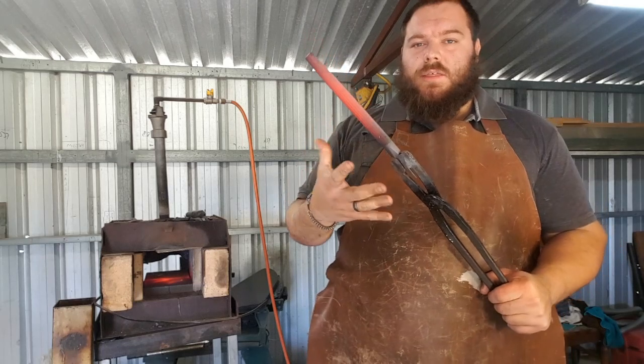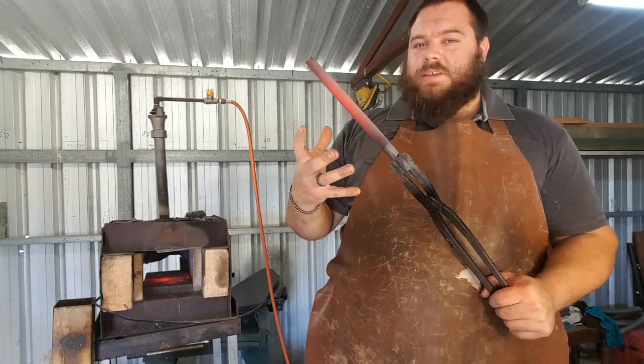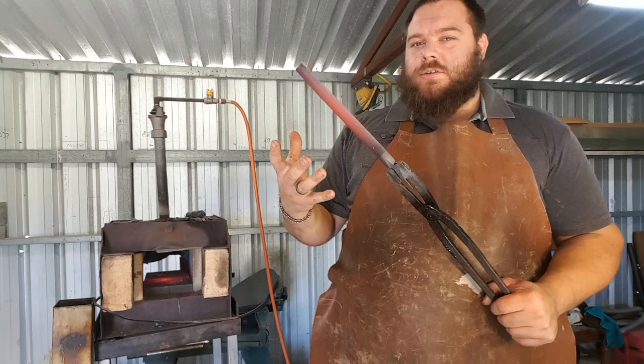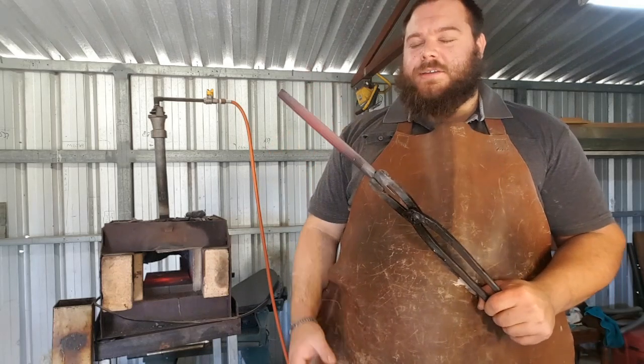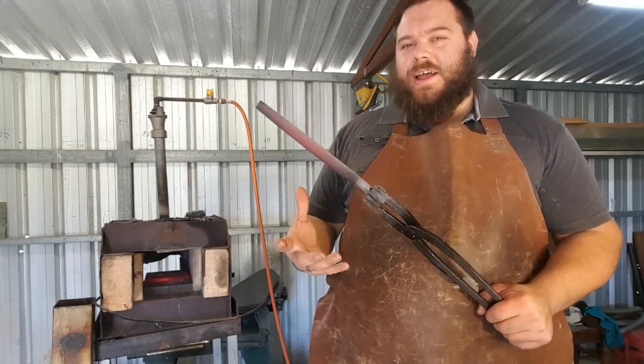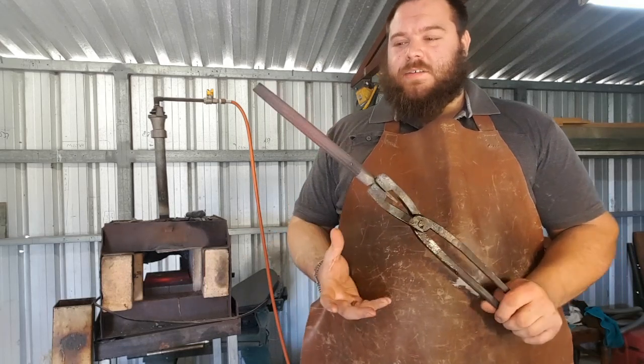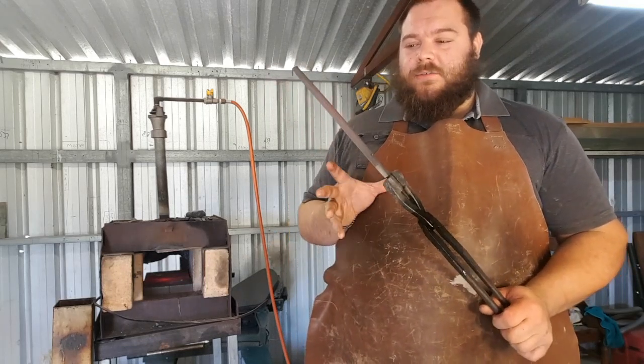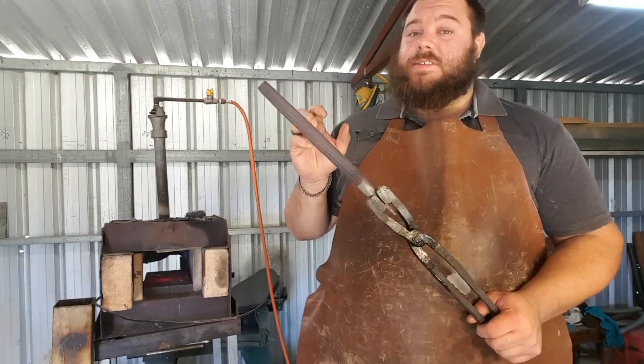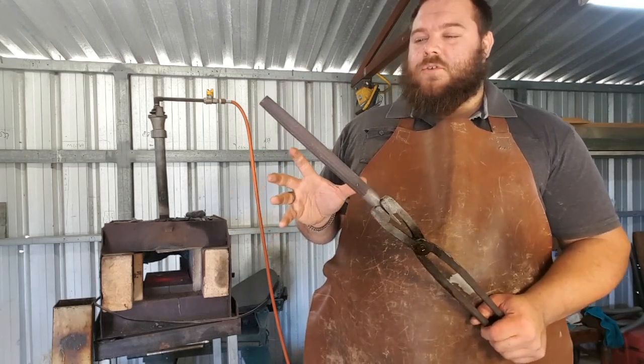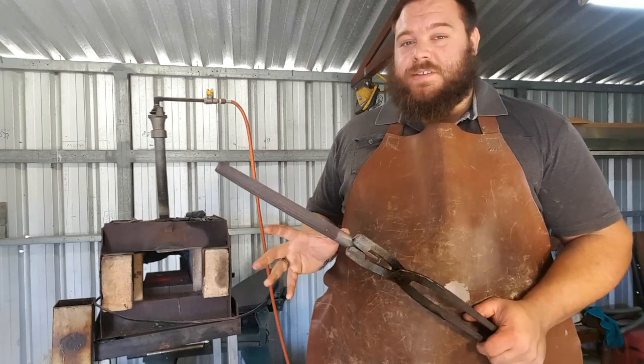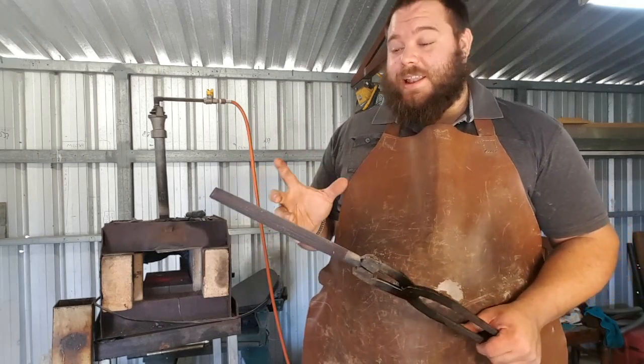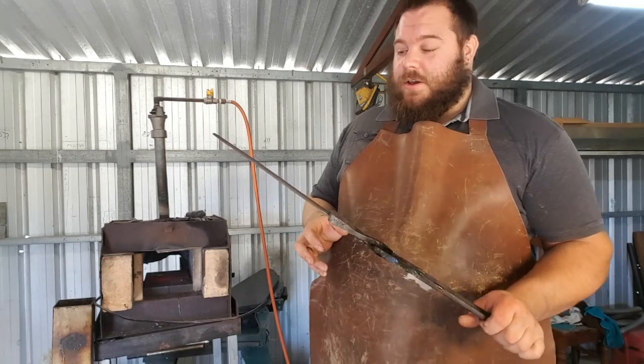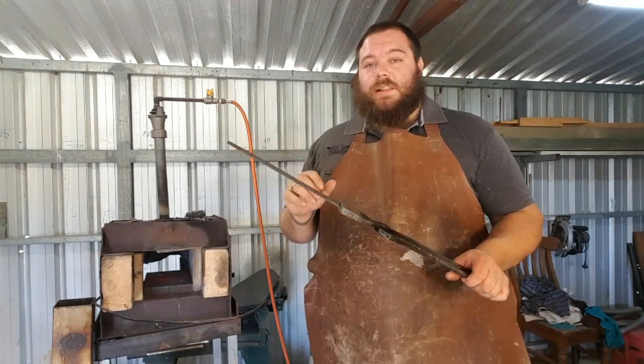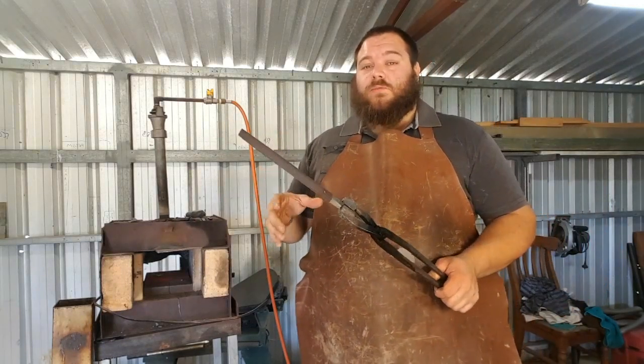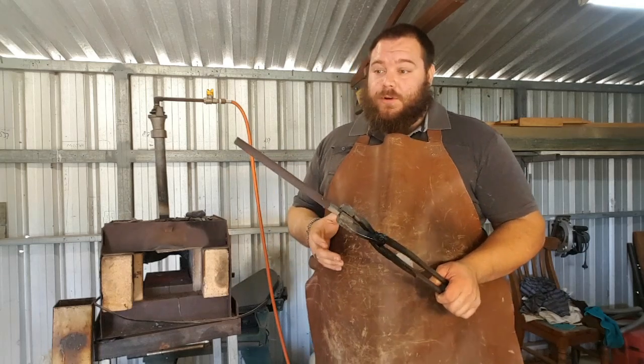So one of the big things with normalization, some people I've seen on YouTube will wave the steel around to try and make it cool faster, but that kind of defeats the purpose of normalization. The whole idea of normalization is to let it relax and cool slowly in still air. And if you're waving it around, you're actually air quenching the steel, which if it's high enough carbon, it'll actually quench it somewhat. So the main thing is to keep it still. Even better would be to put it on some refractory bricks.